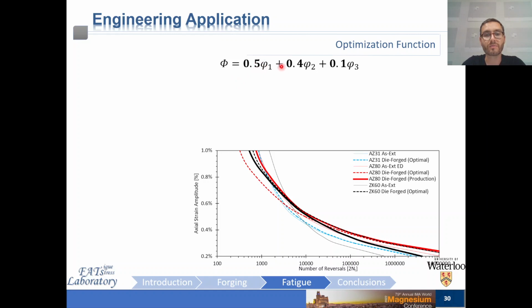The first term, phi1 here, addresses the necessity for the component to have high strength and toughness. Non-dimensionalizing these individual property attributes against the maximum observed over the wide range of processing conditions that were investigated as a part of this project allows us to have a term which reaches a maximum value of unity, or 1. So that's how these terms become non-dimensionalized, as you can see here.